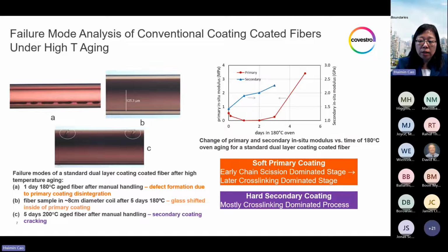And here's the actual illustration of how a fiber coated with a conventional urethane acrylate-based dual layer coating system degraded under high temperature aging. Picture A shows a pipe fiber after just under 1 day of 180-degree aging. Even from handling alone, it easily formed defects in the primary coating, shown as cavities. This is because the primary coating at this point had already turned into a soft gel after the network broke down from the chain scission process.